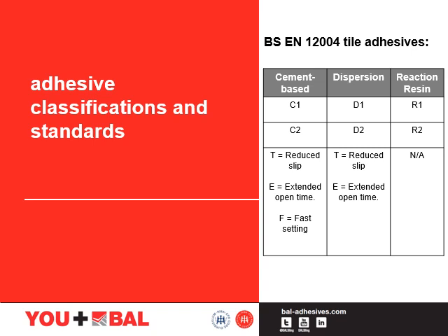Moving on to the classifications, we have 1, which is a normal adhesive, and 2, which is an improved adhesive. This meets the requirements for additional characteristics. Then we have a lettered system. F is a fast setting adhesive, normally cementitious only, and that achieves 0.5 newtons per millimetre squared within 6 hours. T, which is non-slip, is normally used on walls, and E is an extended open time, which is over 30 minutes. This is for cementitious and dispersion adhesives only.